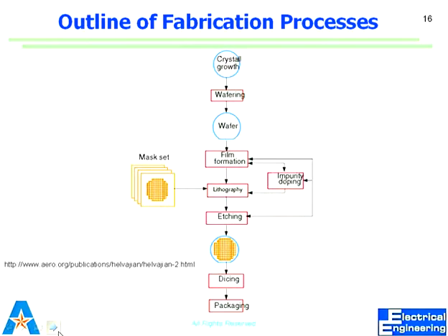So the design of the process, how we integrate the whole process, has to be optimized. If I put a simple example, if I put a metal on a wafer, maybe to make interconnect, now, can I do 1,000 degrees centigrade oxidation? Think about it. No, because metal is vaporized, right? So the whole process has to be optimized and streamlined to know which can come after what. But yes, if I have metal, I can do PECVD, plasma enhanced CVD, to deposit oxide. I cannot grow oxide then, but I can deposit oxide.